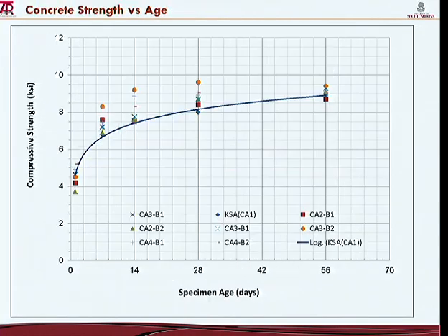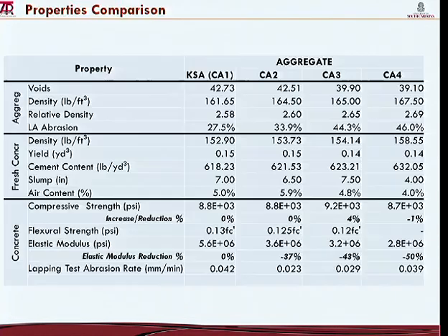LA abrasion values. And the hypothesis here is that the weathered aggregates have fault planes inside the aggregate. So when you put them in the LA machine, all this banging and suffering, it breaks them apart. But when you have them confined in a concrete mortar and that mortar hardens, then the resistance is better than the limestone.